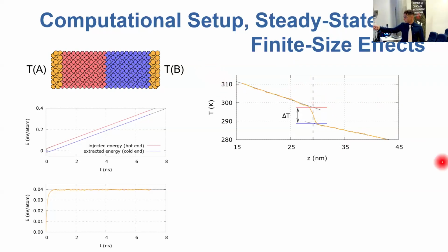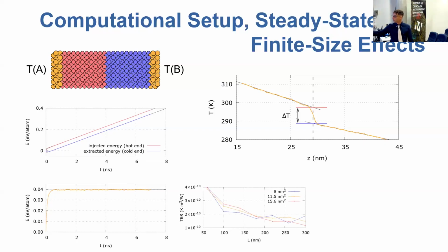We projected the two lines on the interface, and from this, we extracted the temperature drop at the interface. Then, from the slopes of the injected or extracted energy, they're basically the same in the steady state window, we could derive the heat flux across the junction, and from this we could derive, from the definition, the TBR by taking the ratio between the temperature drop and the heat flux.